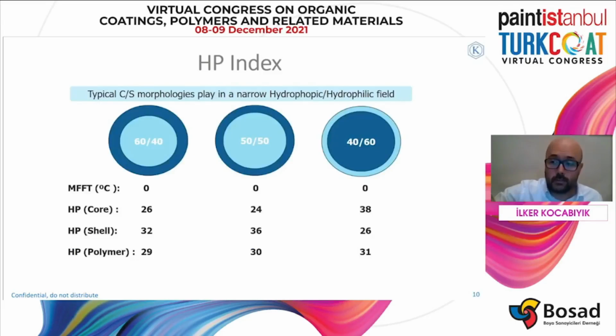Achieving both film elasticity and water resistance targets with limited monomer options forced the polymer producers to work in a very narrow field of experiments. In this example, we see three different heterogeneous acrylics with the same monomer compositions with varying ratios in the core and in the shell, such as 60:40, 50:50, and 40:60. Although the calculated HP index of the polymers is almost the same, around 30, we are able to manipulate the HP index of core and shell in a wider range, and this can affect the water resistance significantly.